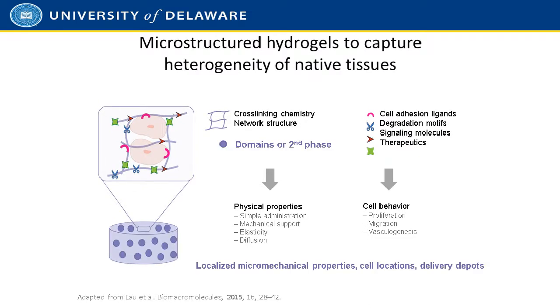We seek to do this by adding a secondary component that allows the gels to be microstructured. These domains, or the second phase that we introduce into the materials, is intended to enable the localization not just of micromechanical properties in the material, but to allow us to control where cells can migrate and proliferate in these materials, and also to serve as delivery depots.